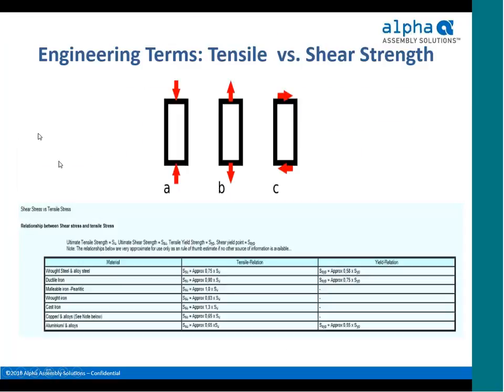One thing to keep in mind, too, is that we have tensile, compressive, and shear stresses on solders. The ones we typically try to test in solder joints are tensile stresses, where we're pulling the solder apart, or shear stress, where we apply stress lateral to the actual connection point. Solder joints tend to be pretty good in compressive stress. That's not really much of a concern, so we don't see a lot of work to quantify that.